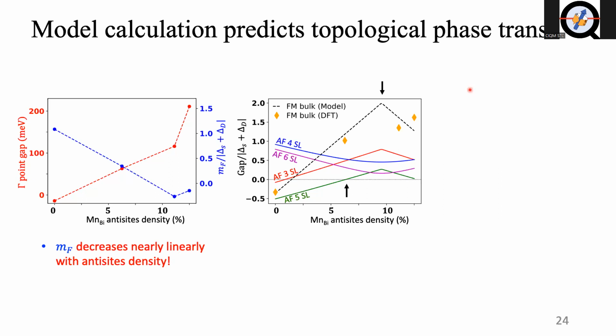But if you keep increasing it to really high, you can see there's a transition. They all have a transition. There's a turning point at about 9%. So what does that mean? That means that the exchange coupling from those anti-site defects is actually high enough that it overtakes that from the middle manganese layer. So it's pretty interesting. This model can capture this.